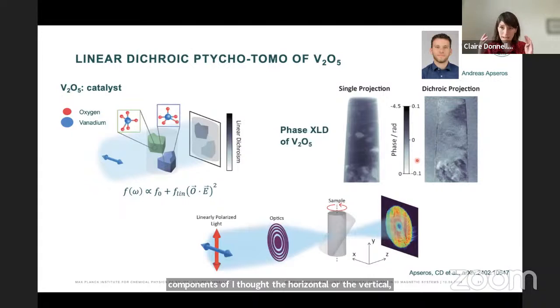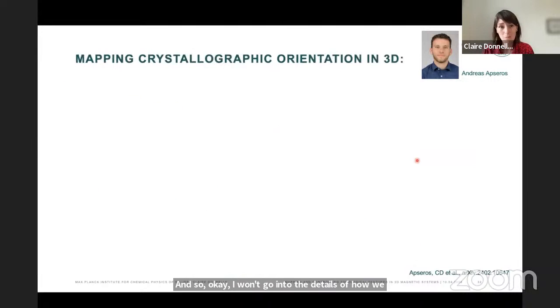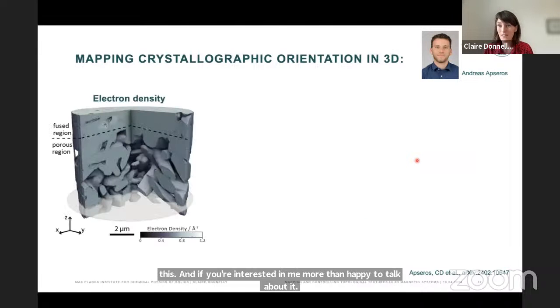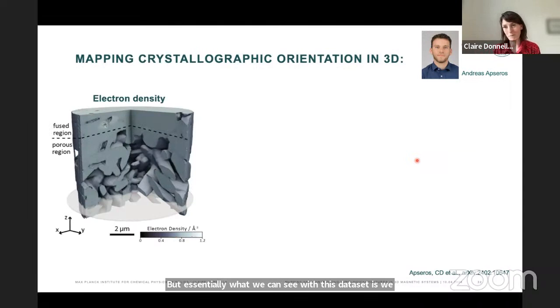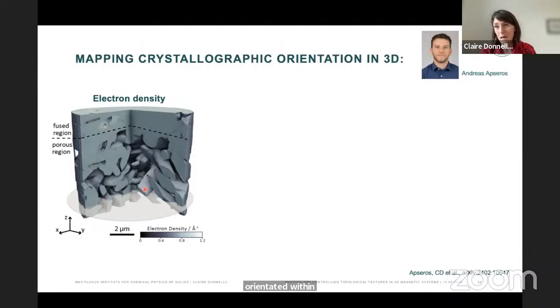What we do is combine this concept again with multi-tilt axis tomography in order to measure enough data to reconstruct our 3-dimensional orientation field. I won't go into the details of how we did this, but if you're interested, I'd be more than happy to talk about it. Essentially, with this data set we already get a number of different sets of information. First, purely from the non-resonant imaging, we get the electron density, which allows us to map the internal structure of our sample. We can see that it's formed of what look like grains or pieces that are randomly orientated within this pillar of about 5-6 micrometer diameter.